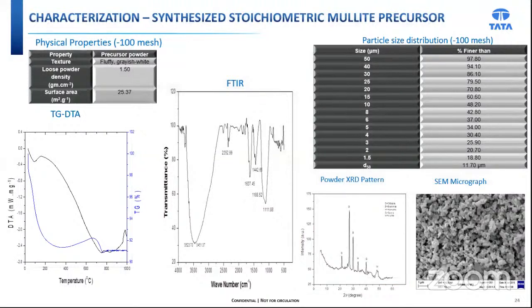This is the characterization of the stoichiometric mullite precursor. The texture of the precursor powder and its optical appearance clearly indicate the presence of mixed phase ingredients. The absorption band appearing in the 700 to 750 centimeter inverse region is assigned to the stretching vibration of AlO6 octahedral units.